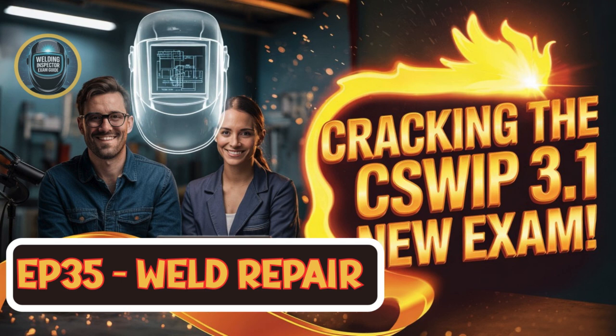Precisely. The reason for failure is absolutely vital for in-service repairs. You also need to know the specific material type and, ideally, the chemical composition for metals. If that cause-effect analysis isn't followed through really thoroughly, the repair is often unsafe. Sometimes, frankly, disastrously so. It's all about preventing a recurring, potentially catastrophic issue. Okay.